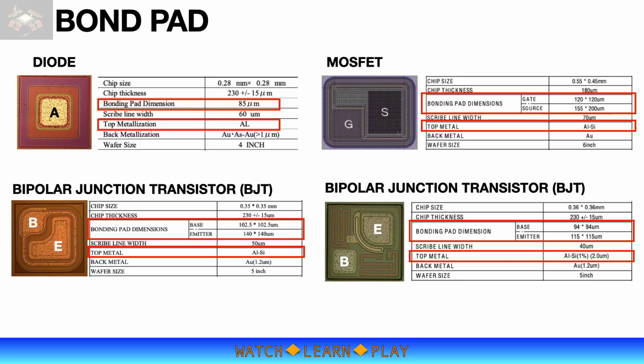The top right image is a MOSFET die which has two bond pads, which are the gate and source. Bond pad metallization is aluminum with 1% silicon and dimensions are over 100 microns. The two bottom images are bipolar junction transistors or BJT. The top side has two bond pads which are the base and emitter. Similar to MOSFET, bond pads are approximately 100 microns or larger and composed of aluminum with 1% silicon and is 2 microns thick.